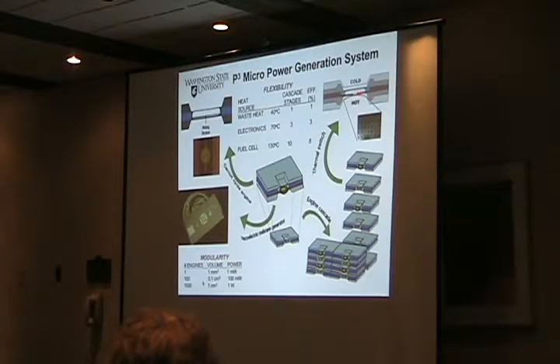And some of what we've been doing in terms of how we structure these materials is looking at thermal switches that can transfer heat in and out of the cavity as we flex the membrane from a hot side to a cold side. The thermal switches we made, about the best we can do right now is about 3,000 C per second in terms of rates, which is pretty good, using mercury or gallium droplets.